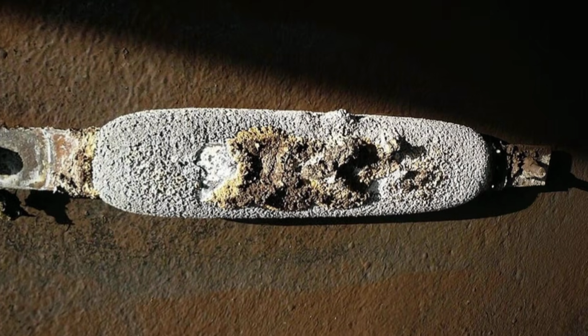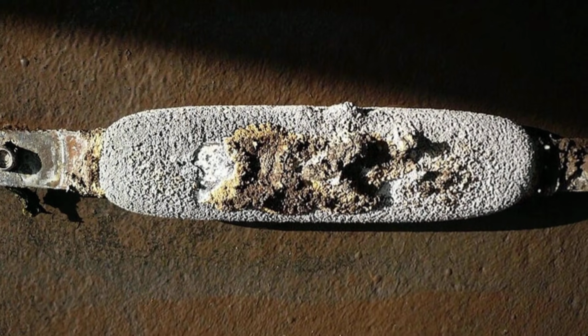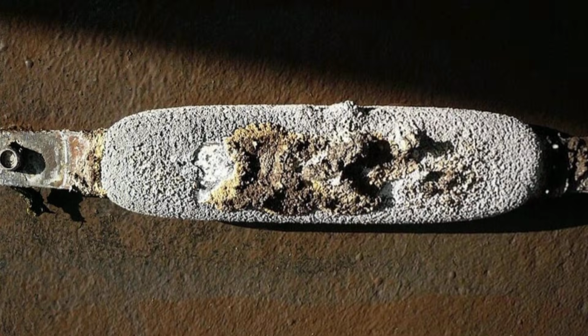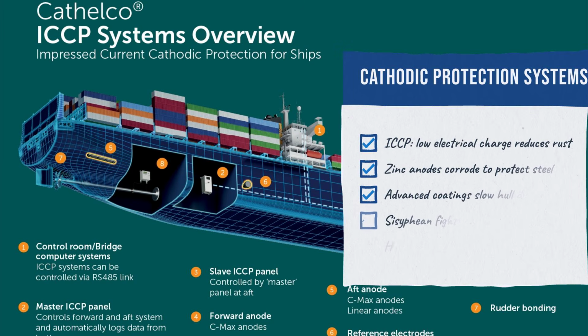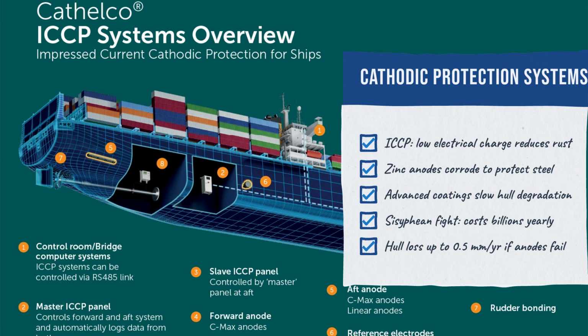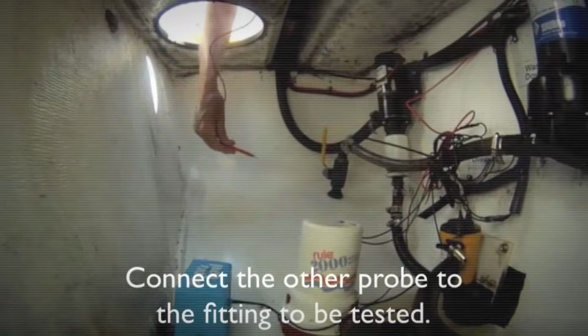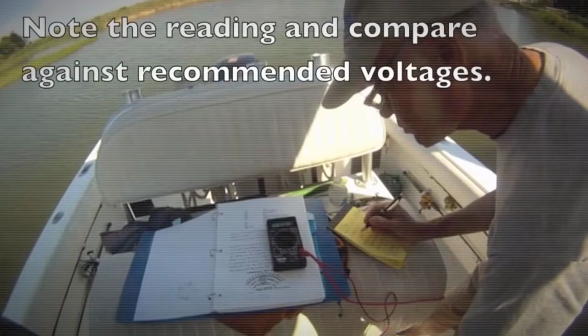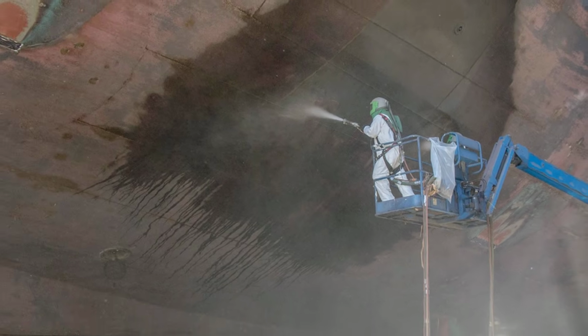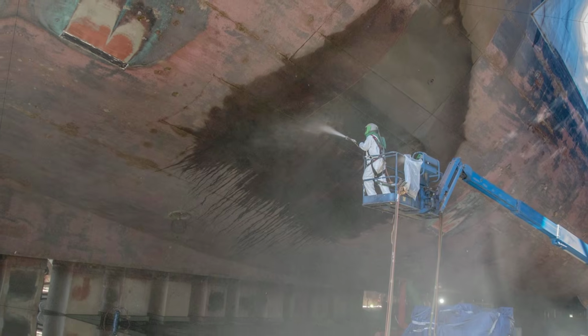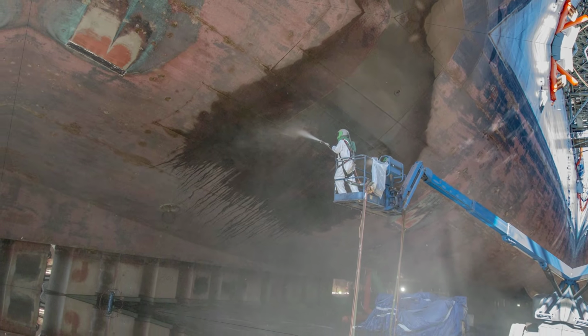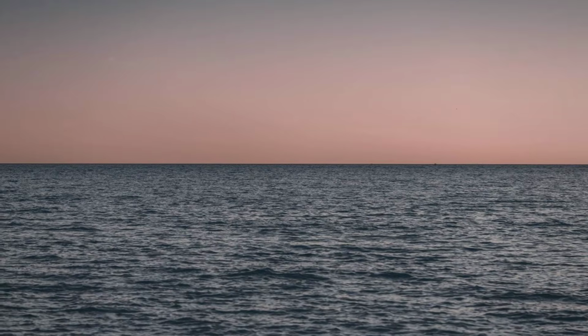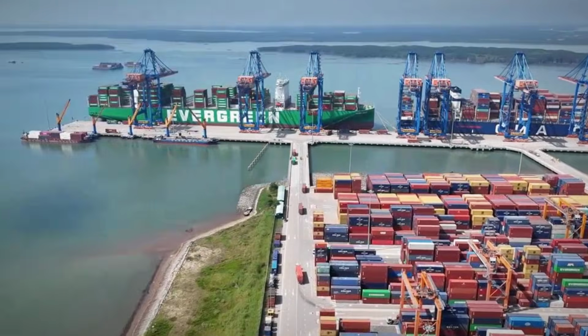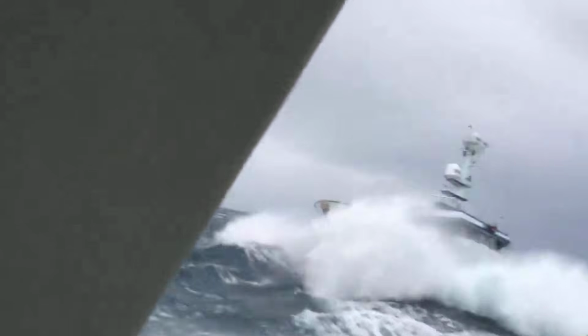Engineers fight it with zinc sacrificial anodes bolted to the hull, blocks of metal that corrode preferentially in place of the surrounding steel. They also employ impressed current cathodic protection systems that send low-level electrical charge through the hull to interrupt the electrochemical reaction. They also apply multi-layer coating systems to freshly blasted bare metal in dry dock, to tolerances measured in microns. And still, 6 months later, the streaks come back, not because the engineering fails, but because the sea never stops and the ships never rest.